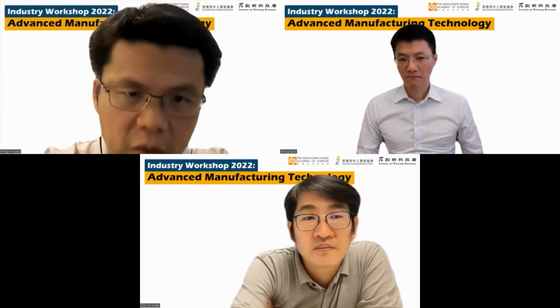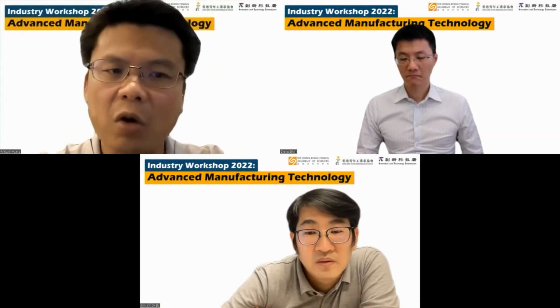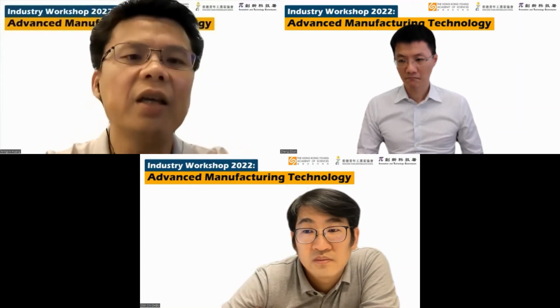Very clearly, we compare the tensile properties, the mechanical properties. The strength can reach about 500 megapascal, which is very similar to normal stainless steel. The elongation reduced a little, but it's still sufficient for any application. We can still go beyond 30% tensile uniform elongation. So it's quite ductile, it's quite strong, and behaves like a normal stainless steel. Of course, there is one drawback.